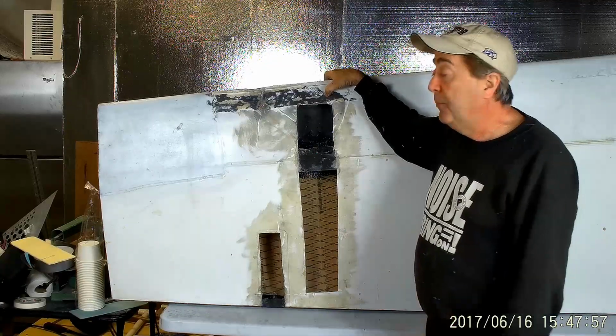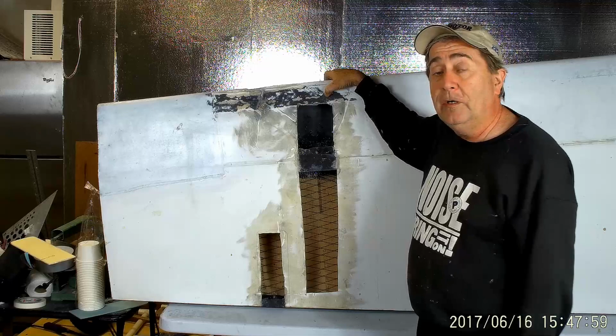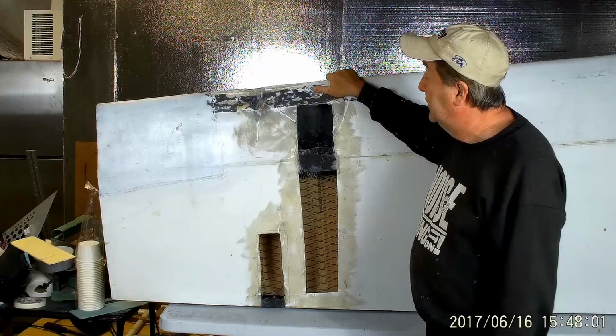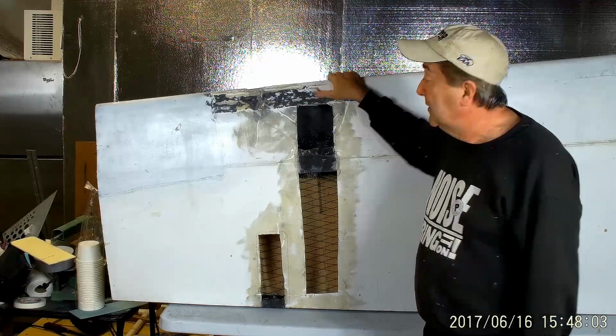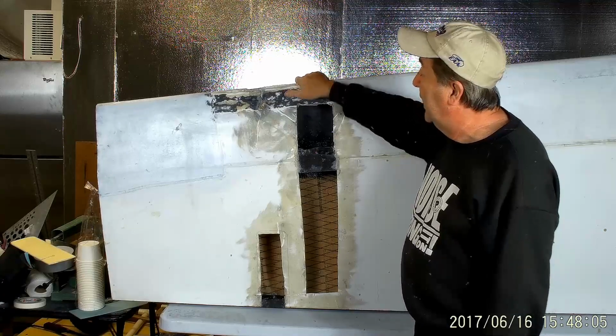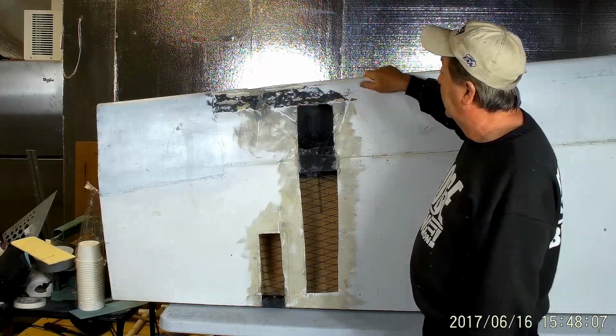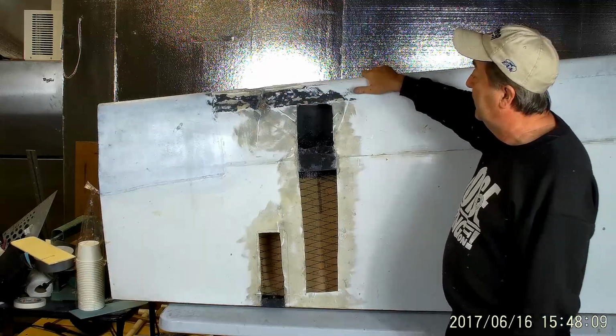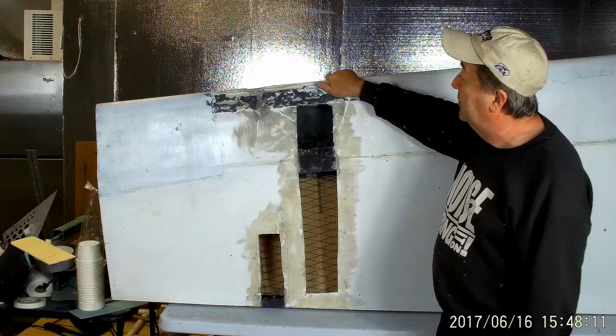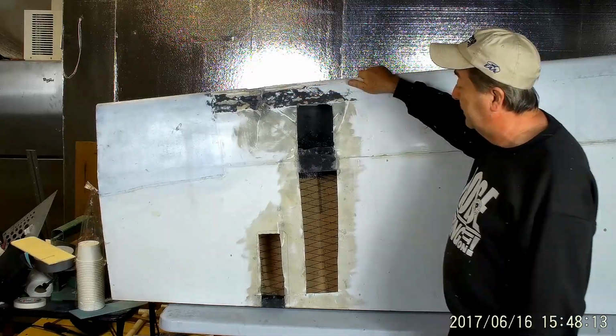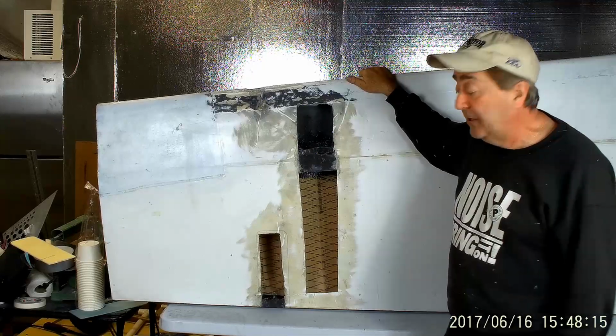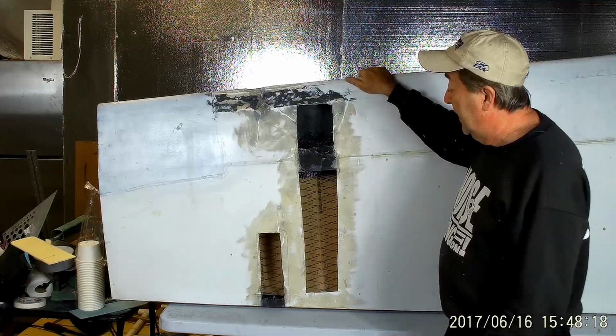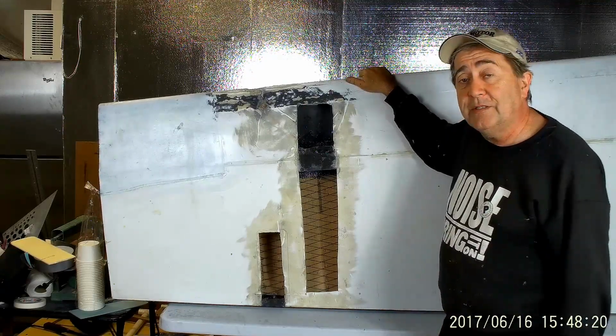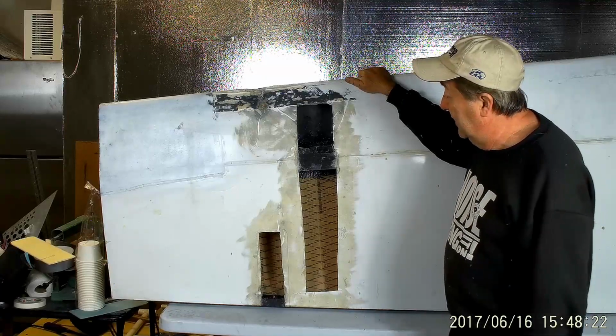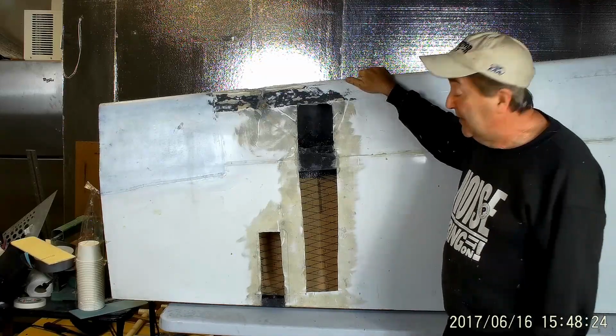I've now changed that process, eliminated the honeycomb core, and switched from Kevlar to fiberglass, and all of those problems have been resolved. But I had to do quite a few change-outs here on the leading edge. I had to strip off the Kevlar, put on some carbon fiber, and fill some spots. That was the first go-around of adjusting the design. Then the wing was dropped once in a test, and there were minor repairs that I did at that time.